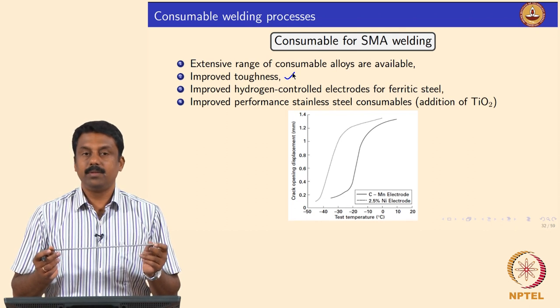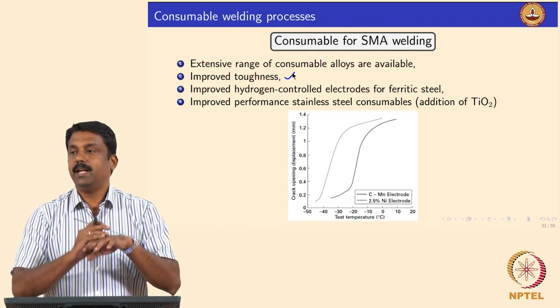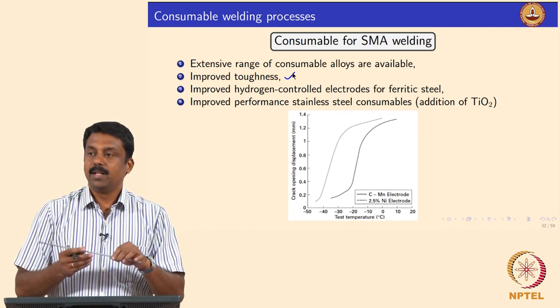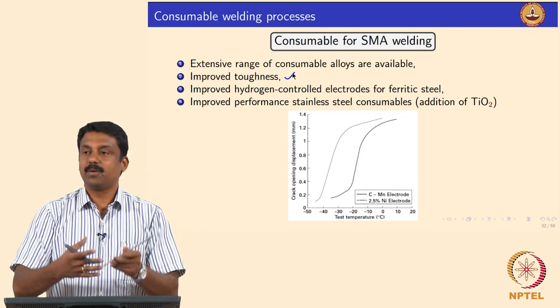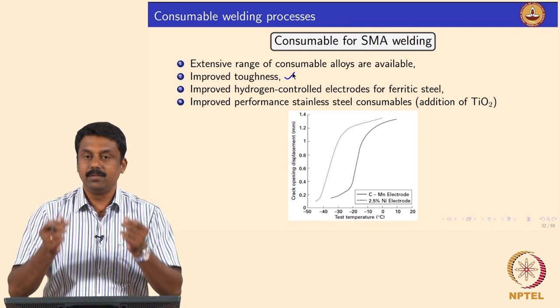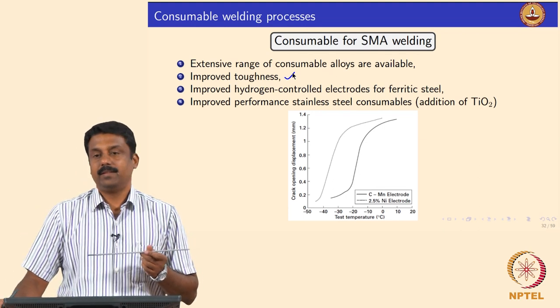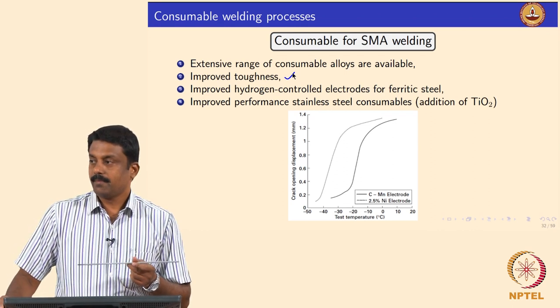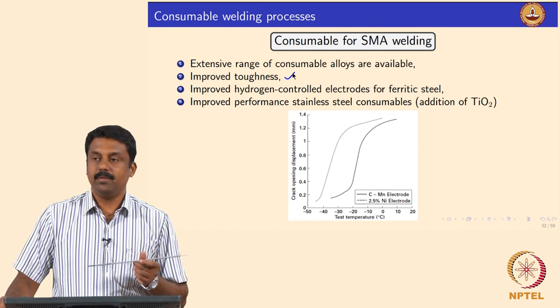When you weld with an electrode that has been exposed to room atmosphere, you generate hydrogen by disintegration of the moisture. This leads to hydrogen diffusion in the weld pool and subsequently the weld undergoes hydrogen embrittlement. When you receive stick electrodes from the manufacturer, they come in a humidity-controlled envelope. Once you open the envelope, you need to keep the electrodes in a controlled atmosphere chamber, or preheat the electrode to 100–125°C (not more than 150°C) before welding to ensure condensed moisture is evaporated.